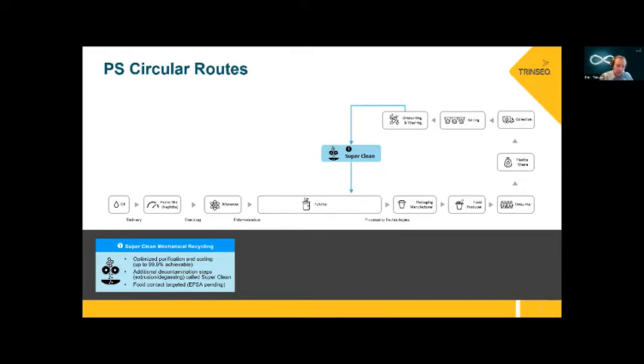What's this all about? This is essentially the adoption of what is known from PET bottle recycling. At the beginning of this process, you start with, let's say, a purity of 97% of polystyrene. With some extra washing, purification and sorting steps, you can achieve, as stated here, up to 99.9% polystyrene. With this high purity, the consortium is currently investigating whether we can get European Food Safety Authority approval, EFSA as stated here. That can be adopted to polystyrene currently, we believe, in quite an easy way, as most of the contaminants are filtered out, and that can be a viable solution within the mechanical recycling stream.